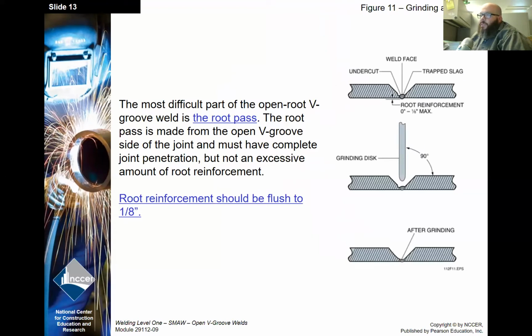The most difficult part of the open root V-groove weld is the root pass. The root pass is made from the open V-groove side of the joint and must have complete joint penetration, but not an excessive amount of root reinforcement. So the root reinforcement should be flush to 1/8 of an inch, just like your reinforcement at the face of the weld.